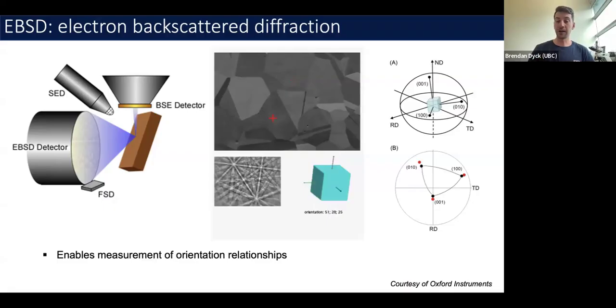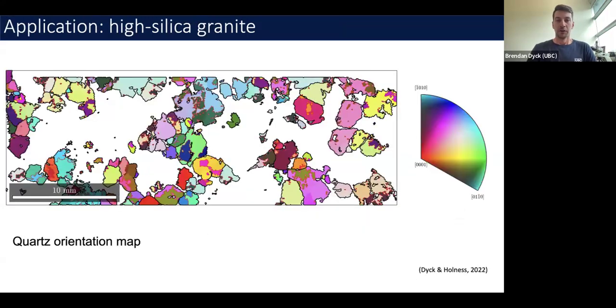So just as a refresher, I'm sure we're all very familiar with pole figures, but if we were looking at, say, a cubic mineral in an upper hemisphere projection of a pole figure, we would expect to see three symmetrically equivalent poles to planes for the 010, the 100, and the 001, right? And so pole figures become a very simple and effective way of communicating this information, and that's also where we tend to look for patterns. So let's take this and apply it to granite. This is a high silica granite. Quartz was the first crystallizing phase, and it ended up developing quartz glomerocrysts.